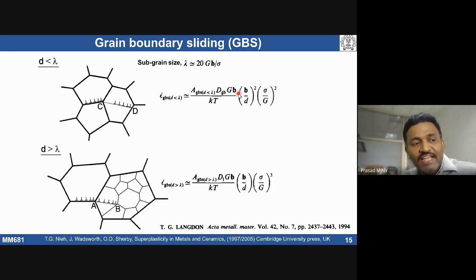But if the grain size is finer than your subgrain size, most of the metallic materials, subgrain size typically falls around 10 micrometers, 10 to 20 micrometers. Even so, grain boundary sliding takes place even in coarse grain materials, but the dependency is going to vary. The grain size dependence and stress dependence is going to be different. When I say coarse and fine, it is with respect to subgrain size.